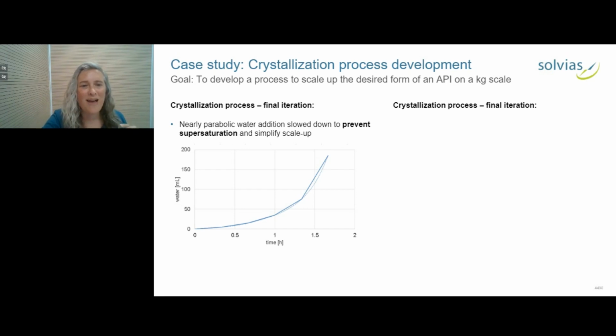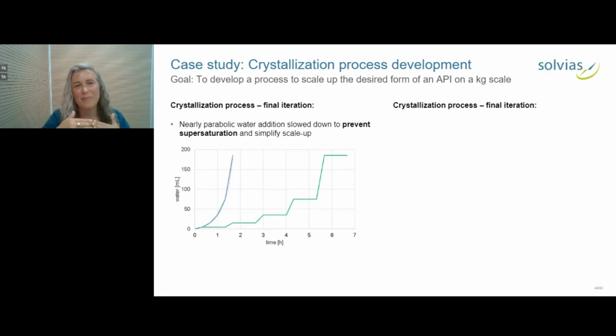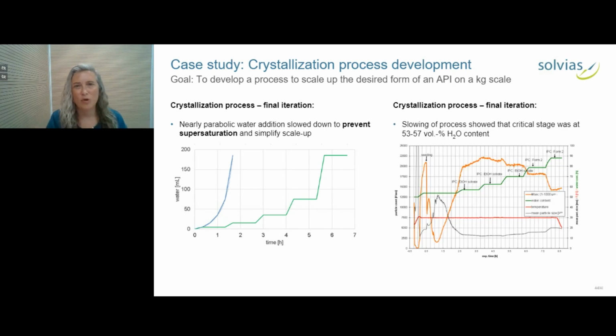But what we found is it was useful to slow it down. So in between each of these ramps, we had a holding time, and that gave the system enough time to really prevent any supersaturation buildup and made the process more controlled. And we were able to identify the critical stage.